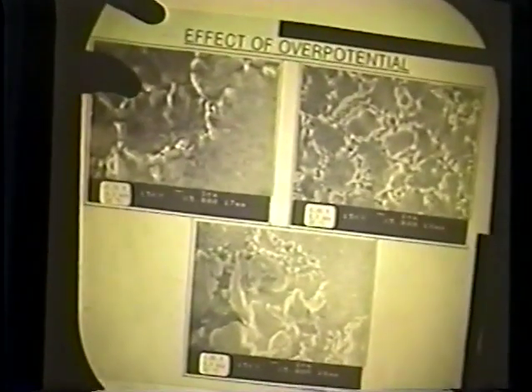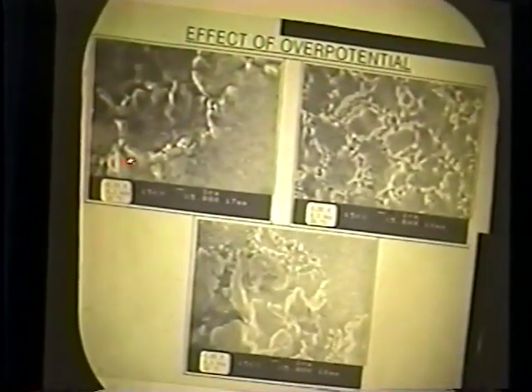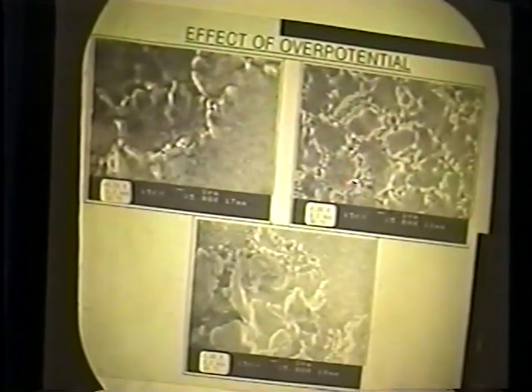Those pinholes, enlarged at 25 and 50,000, we can see are somewhere around 500 nanometers and of conical shape. When we changed potential, at minus 0.35 volts, something similar to what you observed there, 3 to 6 pinholes per hexagon. At minus 0.5 volts, same time, 0.5 hours, we have around 30 to 50 pinholes now spreading around the hexagonal sides of the grain boundaries.